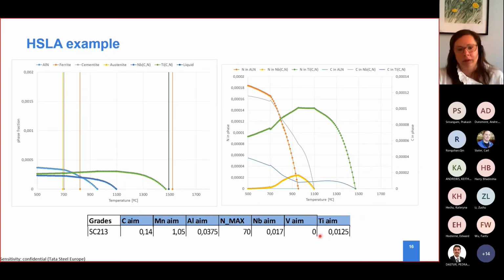So let's use Thermo-Calc. Let's see what we get in a phase fraction versus temperature phase diagram. If I zoom in on the areas where these precipitates are starting to appear, Thermo-Calc is very flexible, but we need to understand what is happening here. Thermo-Calc says each precipitate is a new phase. So that's how it calls it. For us, it's a precipitate. Indeed, if you would see the microstructure, you could consider it a new phase because it has a different crystallographic structure. But depending on their composition and their affinity, and temperature obviously as well, this is equilibrium again, they will appear at different temperatures.